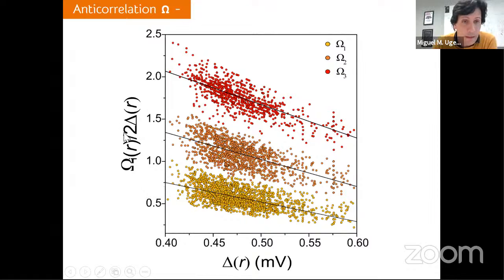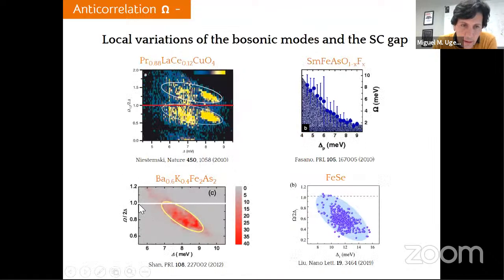Here I show you divided by 2 delta, and the only reason is because the previous papers also do it, because the signature of spin resonances is twofold. First is this anticorrelation, and the second one is that the binding energy of these bosonic modes should be lower than 2 delta. So all these values in general should lie below 1. You see here, here, and here for this.